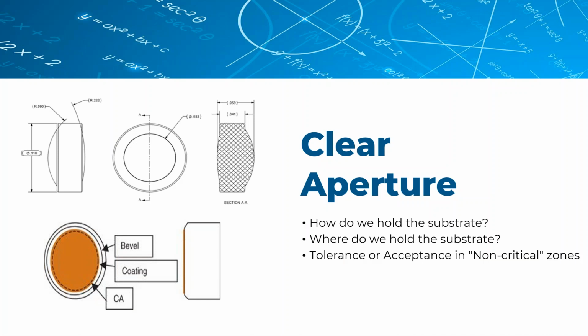So, away from the abrasion, adhesion, mechanical, and chemical interactions, this is clear aperture. Clear aperture is important because it tells us where the critical zones on the coating are, and that tells your coating partner how to hold the optic while they're coating. A unique thing we're tasked with as a coating supplier is that we need to hold a technically very expensive optic that you've injection molded, diamond turned, and fabricated, spending a lot of man hours on expensive material. It's going in our chamber, it's going to be warm, and it's going to be spinning around in deep vacuum. But we're tasked with holding the part as lightly as we can.